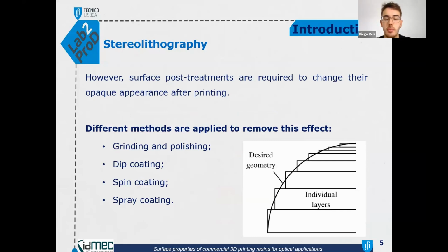However, obtaining optical components by 3D printing is not a straightforward process, because right after printing, the part has an opaque appearance, and this comes from the layer-by-layer methodology. This effect is called the staircase effect, and to remove it, there are different methods that can be applied. For example, grinding, polishing, and coatings with the same resin, for example, dip coating, spin coating, and spray coating. The one that we use is dip coating.